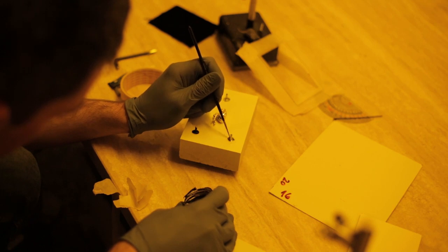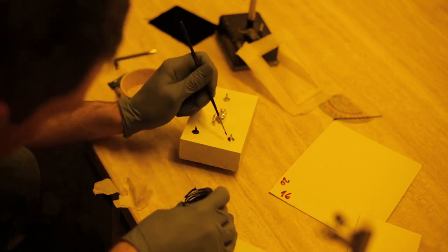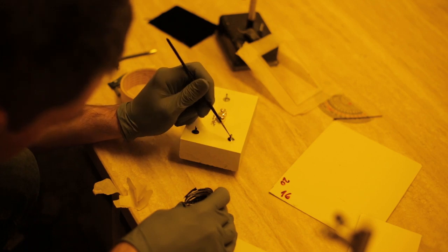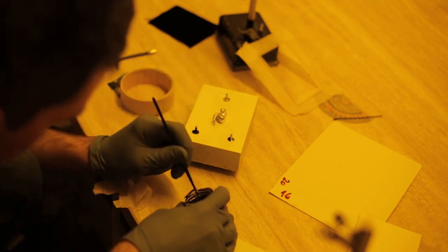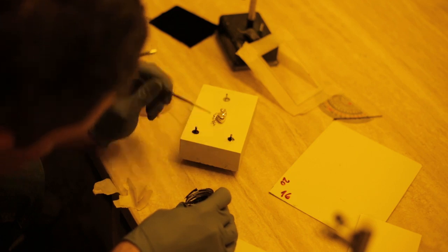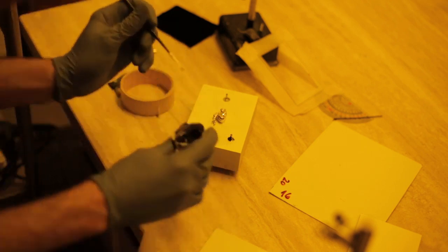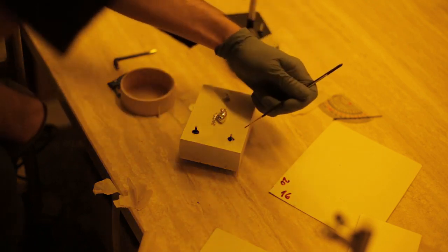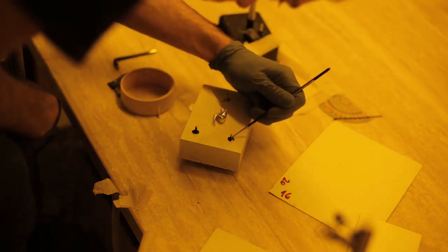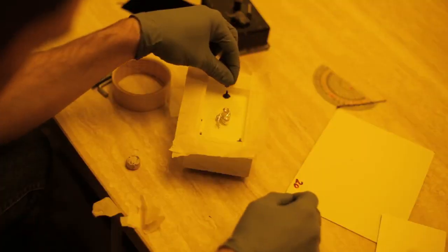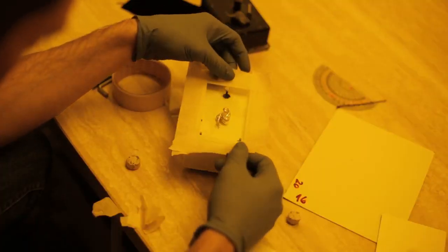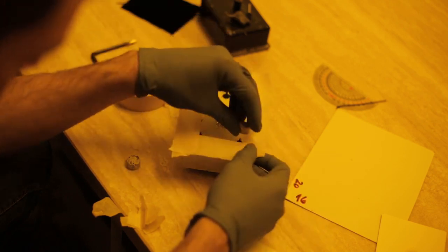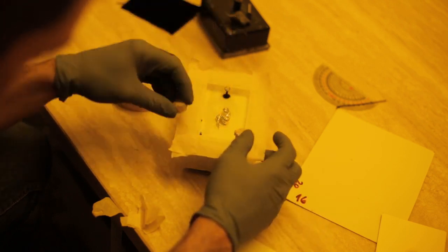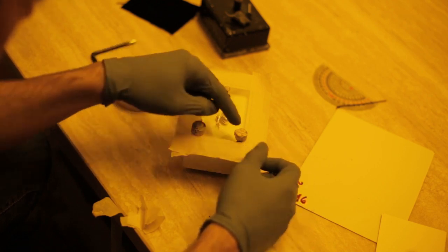With a brush, I paint the spacers black so they won't create unwanted reflections in the hologram. I use acrylic paint for that. You could also use oil paint, which won't be dry by the time of the exposure, creating movement and thus making the nails invisible in the final hologram. I use strong neodymium magnets to fixate the plate to the metal spacers below. The shiny magnets are covered with masking tape, so they don't scratch the glass. The trick will create a very stable recording setup.